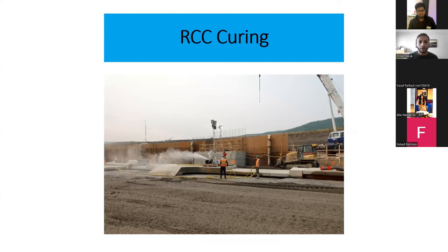So when we are doing the mix design, we need to first set the parameters. First question, curing for RCC is needed just to keep the surface alive. If we are placing one lift above another, we need to make sure the surface is alive so that we achieve good bonding. So curing is needed, but it's not needed like conventional concrete where you pond the surface with lots of water. As you see in the picture, there's a person holding a spray and it's only spraying mist. He's not holding a garden hose and making it pond.